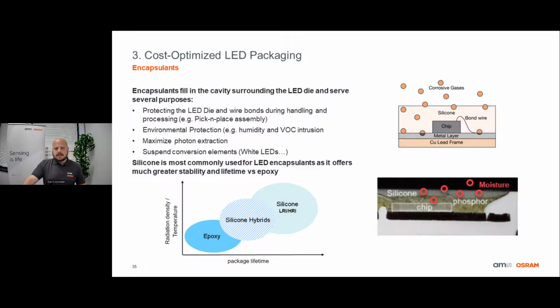Now, LED encapsulants can be made in a variety of different materials, but are typically made of silicone due to its inherent heat resistance and durability. Modern silicone formulations have come a very long way in improving their refractive indexes and are typically referred to as an HRI or high refractive index silicone. It's important to note that HRI silicones are typically harder than LRI or low refractive index silicones. This does help to improve its impermeability, but can increase some of the internal stresses of the package. For phosphor converted LEDs, this encapsulant is also responsible for the suspension of the converter elements.